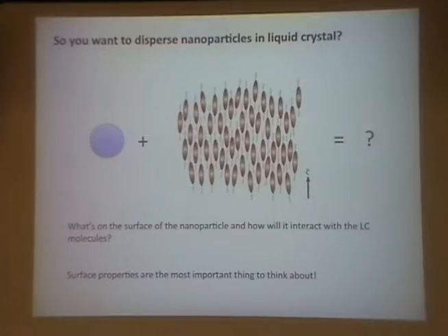Because the nanoparticle is not just this hard piece of semiconductor, okay, it has a surface. And this is really like trying to dissolve something. When a nanoparticle is very small, once you try to incorporate it into the liquid crystal, its surface property is going to fight against you. Look at this typical nematic phase. We have all these carbon chains on the end of the molecules, and we're going to put this particle into here. Think about, well, what is actually going to happen here? Is that going to be favorable to put this thing into the phase? So before you would attempt such an experiment, you should think that surface properties are the most important thing you need to think about.